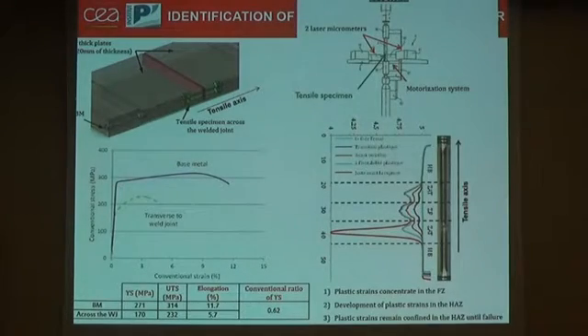First of all, we have to qualify the quality of the welded joints through a coefficient, which is the conventional ratio of yield stress of the base metal and a specimen across the welded joints, which gives an idea of the mismatch of the welded joints. And here, as you can observe, we have a high reduction of the mechanical tensile properties by the presence of the fusion zone, which denotes the high undermatch of the welded joints.